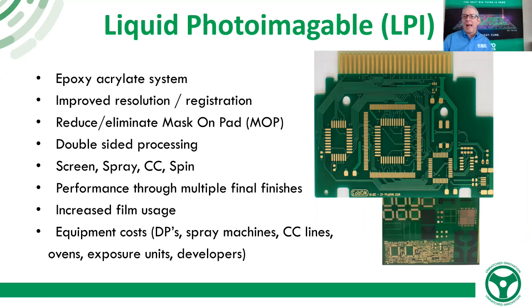LPI was an epoxy acrylate system. We had the acrylates so that it was photosensitive so we could expose it. It had the epoxy for better adhesion and thermal properties. So, but we still had to use a piece of artwork. We still had to put the ink on the board. We either screened it through a mesh, or we had a curtain coater or a spray machine. And we tack dry that. We use our piece of artwork to expose it for the registration purposes. We developed it, we cured it.